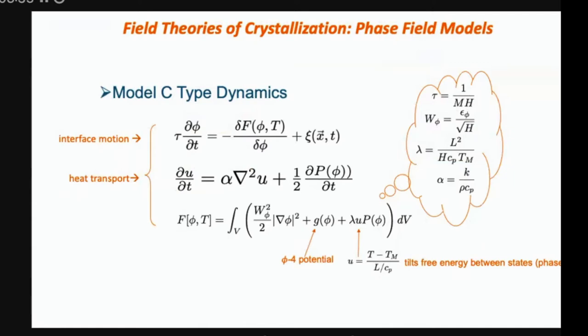Phase field models usually comprise a coupled set of PDEs that kind of look like a reaction diffusion system, where there's a PDE at the top here. We're looking at a single crystal of something that pushes interfaces, and it's driven by or limited by the growth of some coupled slower field, like thermal transport, mass transport. And these two equations are typically derived from some functional that is meant in some phenomenological way to represent the free energy of your system in a closed volume and box with total number of particles.